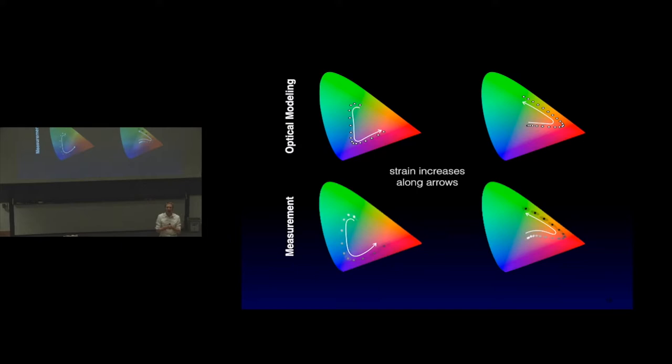We can predict it based on a very simple relation, and it comes out of knowing Poisson's ratio relations, knowing how the material, as it stretches in one dimension, compresses in the other two dimensions. And that's just written in the top part of this graph here. In the data, we show data from 15 stretches. The error bars are from 15 runs, so pretty consistent. And the underlying solid line is a predictive fit, or is fitting using this equation from this model up there. And the only fitting parameter is the Poisson's ratio. And that Poisson's ratio turns out to be 0.46 in this fit, which you would have expected for an elastomeric material. So I think it's pretty cool that this can be predicted and behaves exactly like you would expect it. And that means that we can build fibers that traverse different ranges of color space. And I show here these images of the CIE color space. It's one way of mapping what humans can perceive optically with their eyes, visually with your eyes.